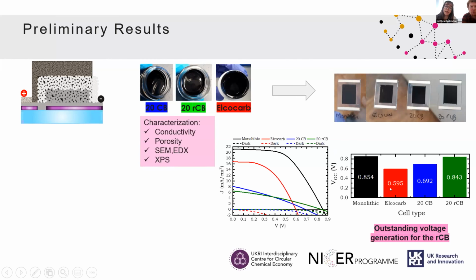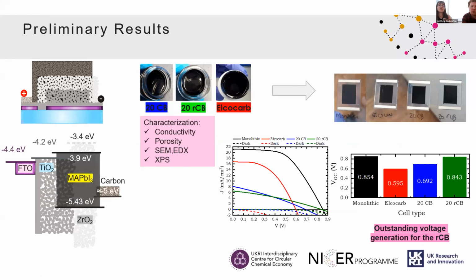As you can see, the ones where we deposited the carbon are lower in efficiency because the process was not optimized in our case. We didn't take thickness into consideration. It was a preliminary test, so it means there's room for improvement. But what was interesting is that we got a really high open circuit voltage compared to, let's say, the commercial stack where we just infiltrated perovskite. And that made us think that indeed, the charge extraction layers are now extracting better.